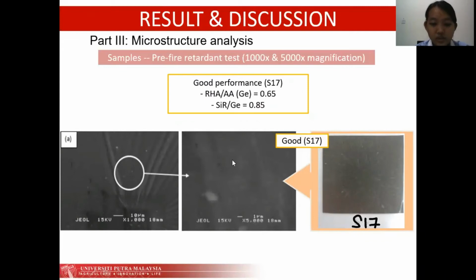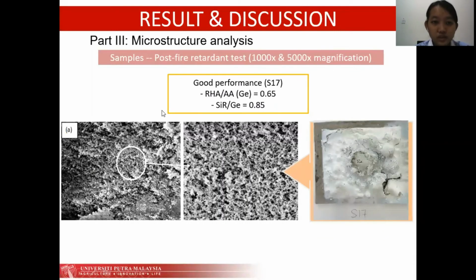At higher magnification, the sample which contains the highest amount of silicone rubber shows a very smooth surface. The excess silicone rubber forms a thin layer and covers the layer of the composite coating matrix underneath. So this is after the fire test. The figure shows the char residue, which is a layer of excess silicone rubber that is porous and continuous. Although there are small holes located in the residue due to the permeating of gases resulting from the decomposition of silicone rubber, the structure is compact, which provides a shielding effect for the layer of geopolymer composite matrix underneath.